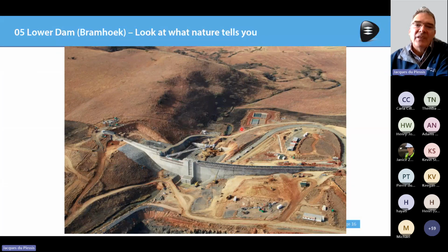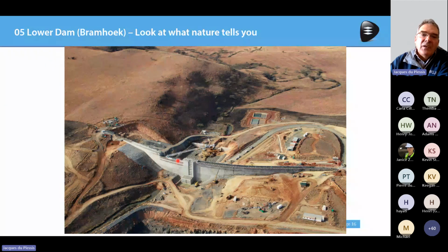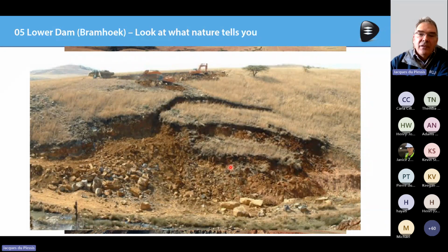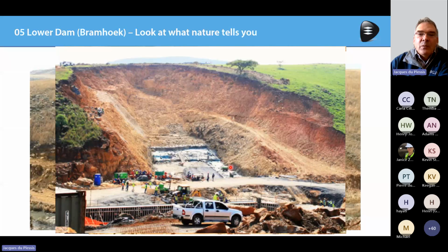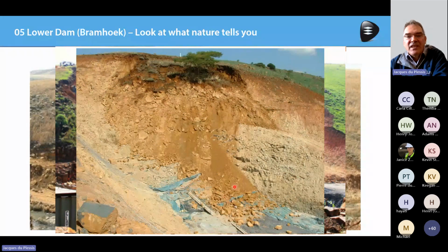Okay, please have a careful look at this photograph, and carefully look at what nature shows you. You can see this material originally was over here, and that material was over there, and this material slipped from there. So no wonder then when the contractor started excavation for the dam foundation against the lower left flank, the material just started slipping and slipping. And when we got to this stage, we thought, no, everything's fine. Look at this tree, and it slipped again. So this resulted, understandably, in a claim by the contractor, which he won in the end.